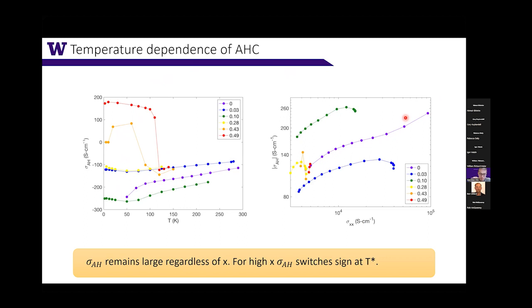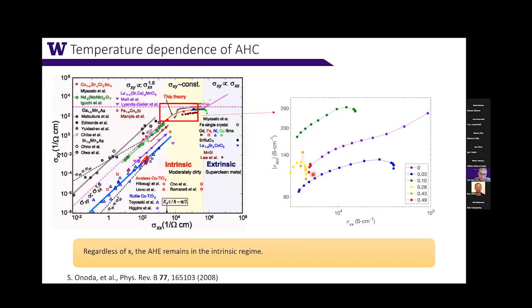Once you start to dope and you introduce disorder, the conductivity is pushed to a much lower value. So if you compare this to this very famous sigma xy versus sigma xx log plot, then you realize that in this high doping region, you're really confining this anomalous Hall behavior to this intrinsic regime.